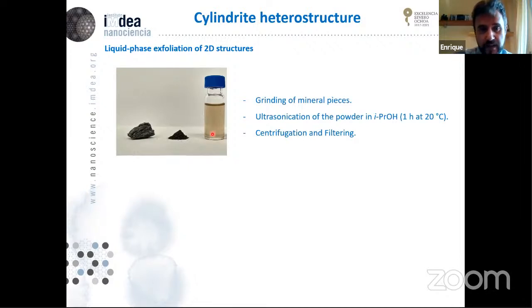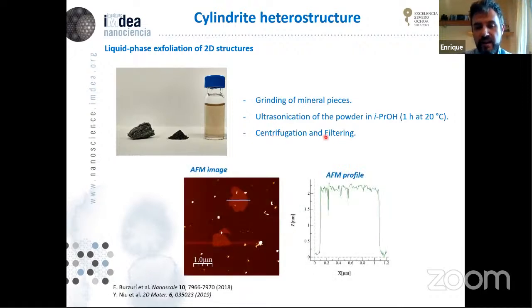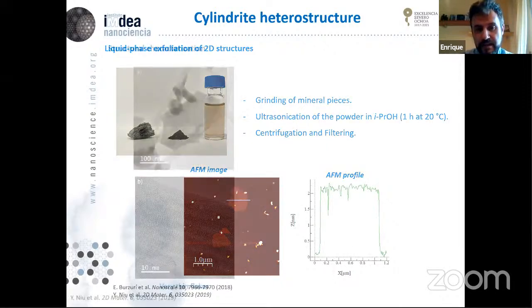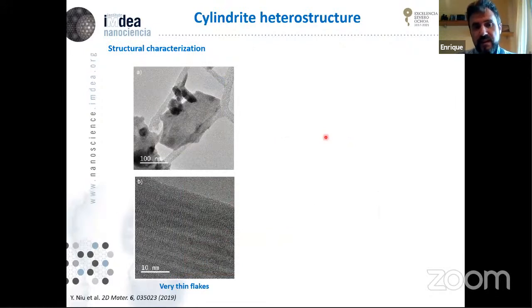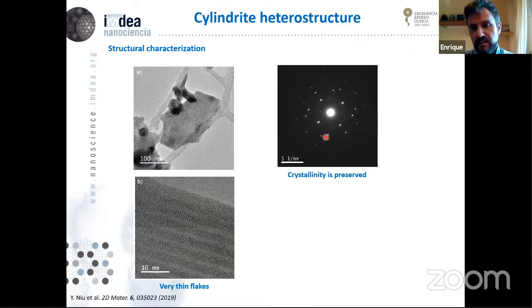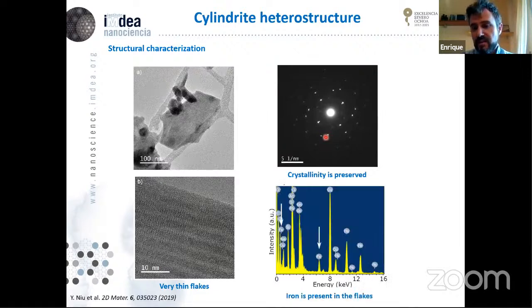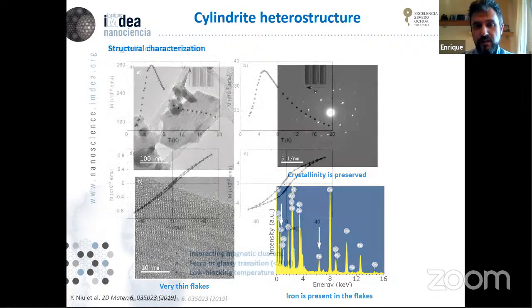This Lucia did. Basically, she grinds the material, she disperses the material in a solution, and by a series of processes of ultrasonication, centrifugation, and filtering, we are able to get very thin flakes. Actually, we are able to go to the monolayer of this material. This is quite an aggressive process, so before using them, we have checked that indeed the crystallinity is preserved. The presence of iron in the flakes is also preserved, which is important.